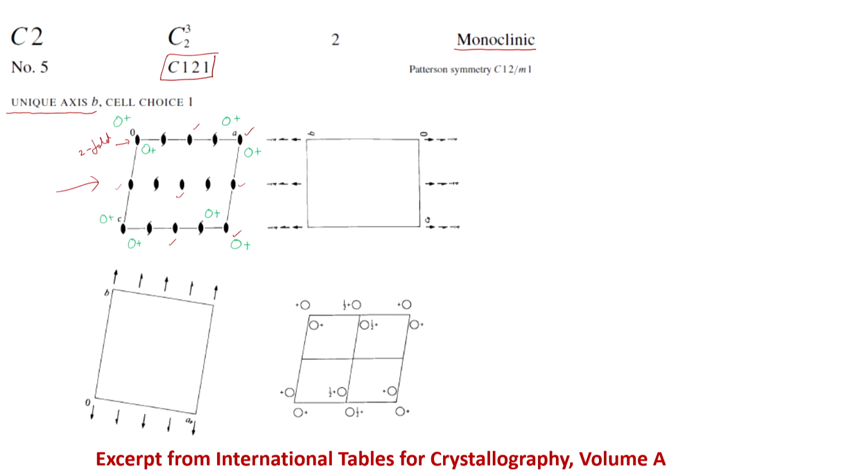And there is another lattice translation as well, which is to the centered lattice point on the C face, or rather we can say on the AB face. So, the B axis is perpendicular to the diagram, and this AB face is going to be perpendicular to the figure. The centering translation is going to be half A plus half B plus 0 times C. If I look at this centering translation, these two motifs get translated to the half plus position.